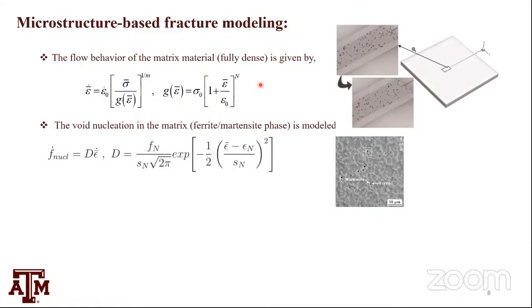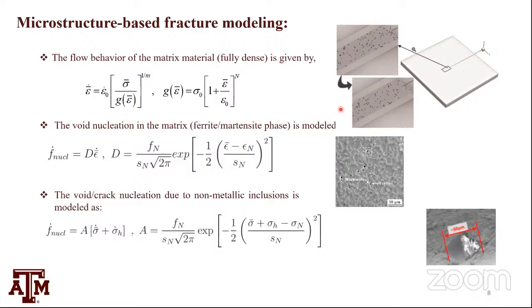Now I need nucleation criteria, because if I have a microstructure feature, it might not have a void, but it may nucleate a void as the deformation proceeds. So I got a material, I got microstructure, and the nucleation criteria follows two relations. Either I can have a nucleation coming from accumulated plastic strain, as shown in this material, or I can have a nucleation of void coming from a hard particle or a soft particle. One follows a mean strain. I have a mean equivalent plastic strain. If I reach that value following a half Gaussian distribution, I nucleate voids. Or based on stress, I have this driving force, effective stress plus hydrostatic stress.